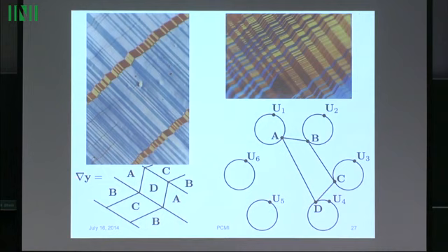That means the gradient of y can be integrated, and there's a continuous function y defined on this domain with exactly those gradients. Okay? And then you take this continuous function, you plot the deformed configuration. It looks exactly like this. Okay? So that's a microstructure. This is not a simulation. This is an observed microstructure in the material, in this particular material, and there's another form of it right there.